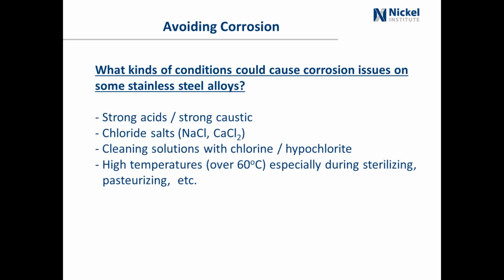What kind of conditions could cause corrosion issues on some stainless steel alloys? Strong acids and strong caustics, chloride salts, cleaning solutions with chlorine and hypochlorite, and high temperatures. And in the case of over 60 degrees C, with the chlorides present, you might get chloride stress corrosion cracking, but higher temperatures increase the corrosivity of an acidic solution.